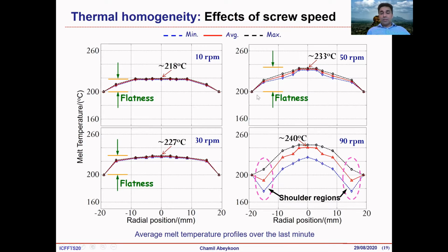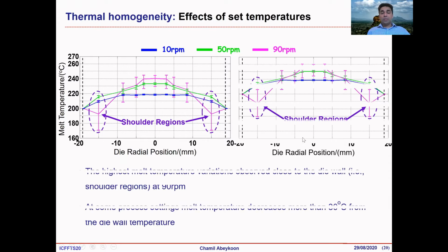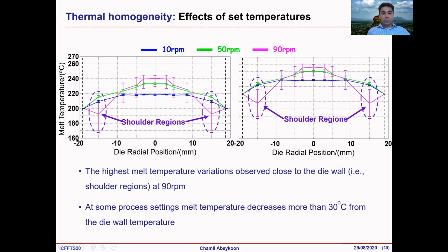This is another indication of how the temperature varies with the screw speed: 10 RPM, 30, 50, and 90. You can see the flatness of the temperature profile is decreasing, which means the fluctuations are getting higher and higher. This is the effect of set temperatures. This is 200 degrees set temperature at the die, and this is 220 degrees set temperature.